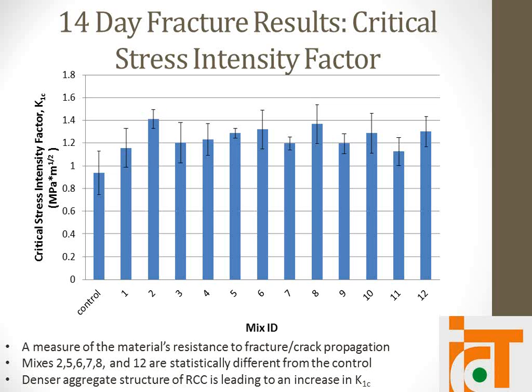And this is where RCC really shows its improvement over typical concrete: the K1C, or the critical stress intensity factor. It's thought that the denser aggregate structure of RCC is interfering with the crack, making the crack path more tortuous, and also halting cracks and preventing their propagation. This control is typical of early age concrete fracture, about 0.9 or 1 or slightly over 1, whereas RCC showed 1.2, 1.4, around that range.